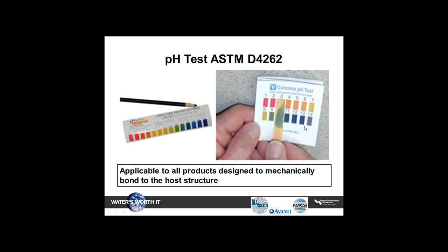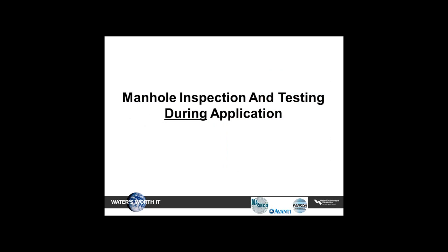There are pH tests out there, which test the pH of the concrete wall before the application of the new coating material. And as Jim also said, this is a technique for determining what type of product is best applied. Is it a low pH? Is it a high pH? Does it require a polymer, or does it require a concrete or cement type surfacing? So these are things that can be checked very effectively.